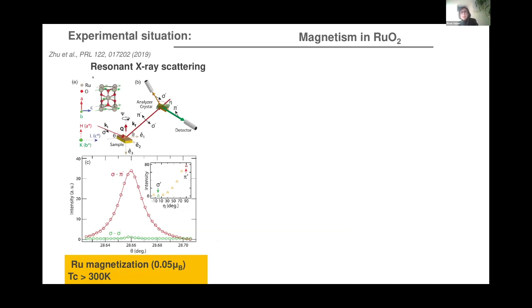For instance, these measurements considering the ruthenium L2 absorption edge in resonant X-ray scattering, where by analyzing the polarization and azimuthal angle dependence of the magnetic Bragg peaks, they could deduce that ruthenium dioxide indeed orders in an altermagnetic fashion. So here is the ordering, which would be to have this altermagnetism.